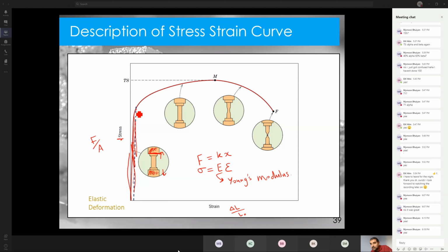The interesting event happens around here. When you go past this stress, you notice how the stress-strain curve is no longer linear, it's actually now rounded. And the reason is the sample is no longer deforming purely elastically. The sample has now yielded, and we call this sigma y the yield strength. For many materials, the yield strength is what you care about. This is what determines whether the material is useful or not.